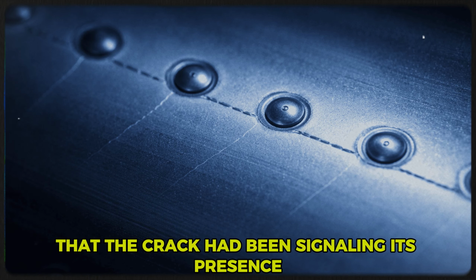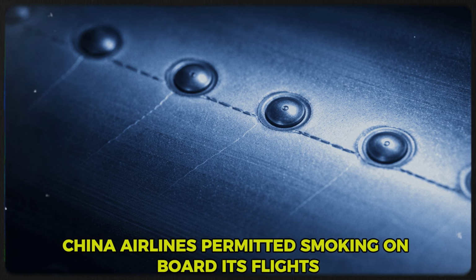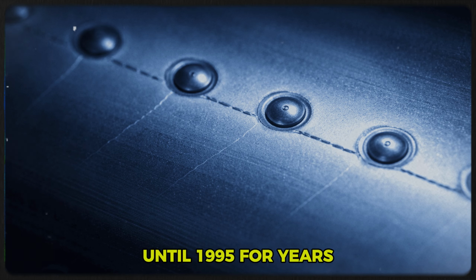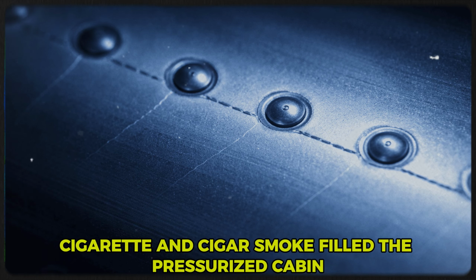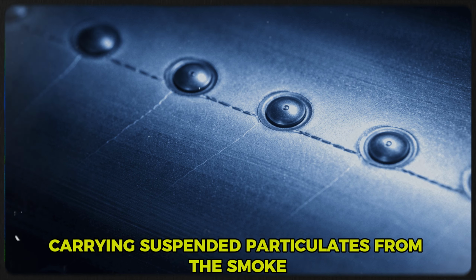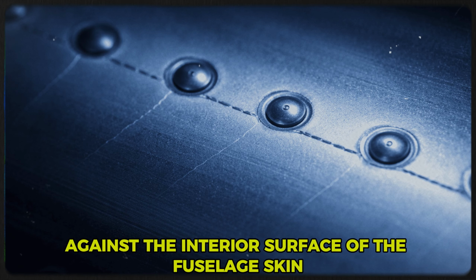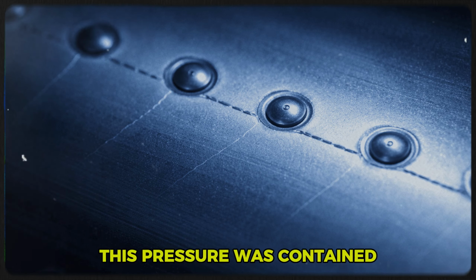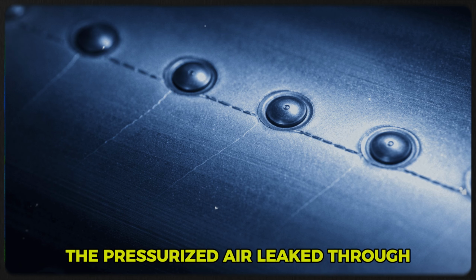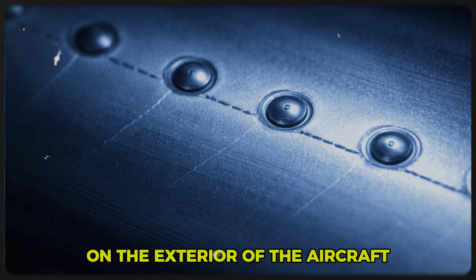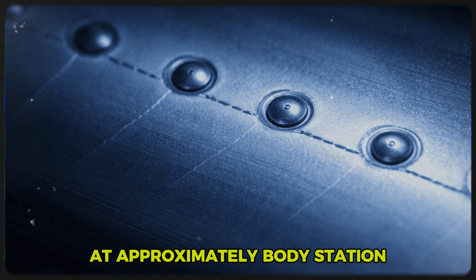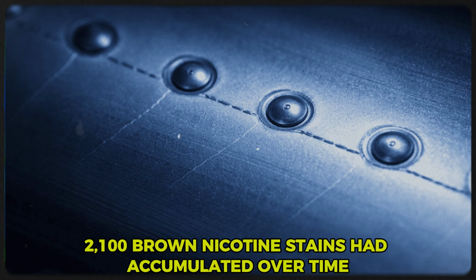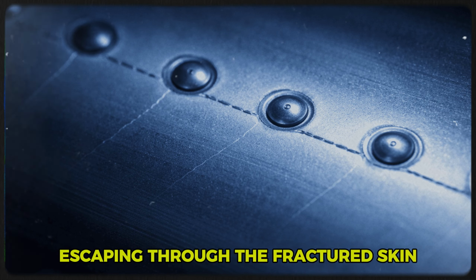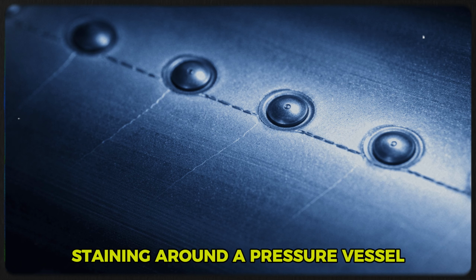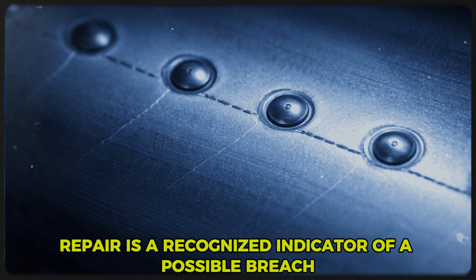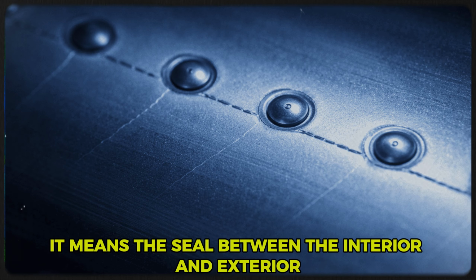There was evidence that the crack had been signaling its presence. China Airlines permitted smoking on board its flights until 1995. For years, cigarette and cigar smoke filled the pressurized cabin. Pressurized air, carrying suspended particulates from the smoke, was continuously pressing against the interior surface of the fuselage skin. Where the skin was intact, this pressure was contained. Where the skin was cracked, the pressurized air leaked through. On the exterior of the aircraft, around the repair doubler, at approximately body station 2,100, brown nicotine stains had accumulated over time. These stains were the residue of cabin air escaping through the fractured skin. Staining around a pressure vessel repair is a recognized indicator of a possible breach. It means the seal between the interior and exterior has been compromised.